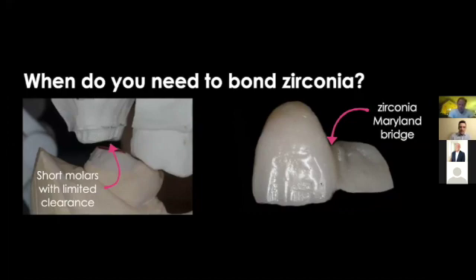For Maryland bridges, which I've done, I always say I've done 2 of those in my entire life. But with the Maryland bridge, there's always the question, should it be Emax? Should it be zirconia? My thought is if you have Emax, even with a higher bond, your failure would probably be a break in the connector, and then you'd have a wing stuck on the lingual surface of the patient's tooth and a pontic in your hand. Whereas with zirconia, debonding is probably the bigger thing you're worried about, and then you at least have the whole thing in your hand, and you can just go and rebond it.